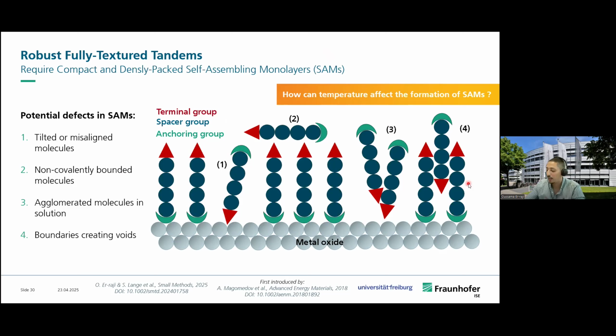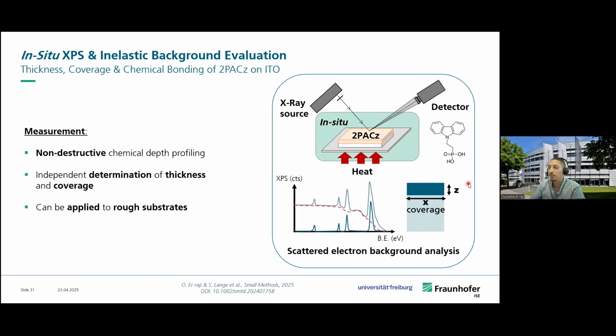this for the SAM? And as a methodology, we used in situ X-ray photoelectron spectroscopy, and we used 2PACz as a SAM. So in practice, we spin coated the SAM, and then we took it to a chamber where we did the annealing variation, in a controlled atmosphere, and we saw how the XPS spectrum changed depending on the time and the temperature. And in terms of analyzing the data, we used the scattered electron background analysis by my colleague here, Stefan Lange, which enables us to get from the background an idea about the thickness of the SAM.